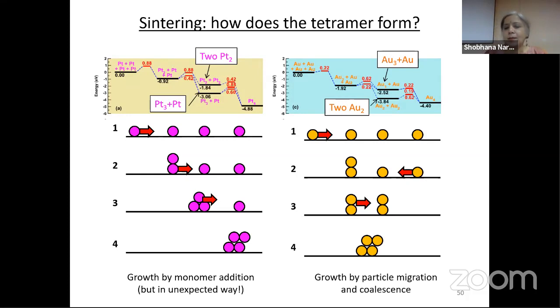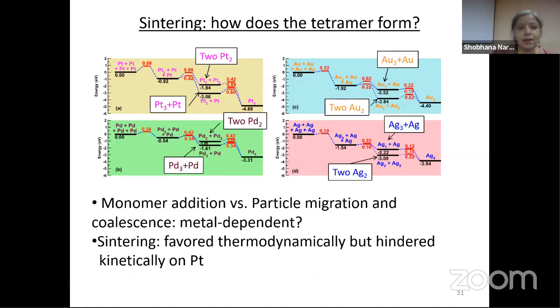Whereas in gold, something quite different is happening. In gold, it is growing by particle migration and coalescence. So these clusters are diffusing and then they're forming larger clusters. So all this information we're able to get just by looking at the diffusion barriers. So it's very rich, the amount of information you can get from the DFT studies we have done. So you can look at this for all the different elements we have studied. It's too much information here for you to take in. So I'll just tell you that it is very metal dependent what happens.